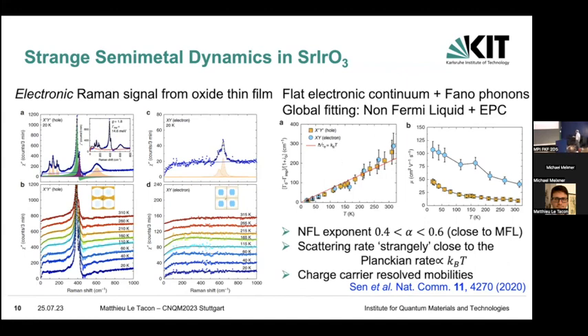And I'm just going to flash here some of the results. The first thing is that the exponent that we got for this non-Fermi liquid was between 0.4 and 0.6, so quite close to the marginal Fermi liquid one. Which is fun because, of course, you have this flat continuum, which has also been observed in the cuprates and was one of the motivations to develop the marginal Fermi liquid phenomenology. The second observation is that the scattering rate we extract from this analysis is strangely close to the Planckian rate, so linear with T. We don't see any logarithmic corrections here, probably because the renormalized mass that we get is still quite modest, a lambda of 3 or something.